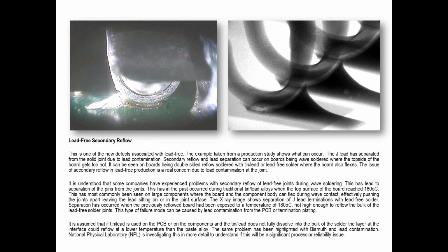Now, secondary reflow as a process issue is, or used to be, where we reflowed something, the boards had components on the top side, and you were wave soldering or selective soldering, and the components reflowed again, and if the board warped or twisted, the joints separated, as you see in these examples I show here. However, in these examples, we're looking at soldering with lead-free solder, but the terminations were actually coated with tin lead. And one of the things that some engineers forget is that if you introduce lead to a lead-free joint, the temperature at which it reflows the second time round is lower.